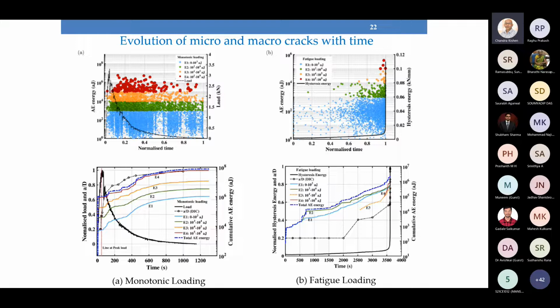But then with increasing crack mouth opening displacement, we see a gradual increase in the low energy and the higher energy events, and later on it becomes more or less constant. Whereas we see an opposite trend during fatigue loading. In fatigue loading, the energy levels E3 and E4 occur only after 70 or 80% of the fatigue life. We don't see them occurring in the beginning. Whereas energy levels E1 and E2 we see occurring at the beginning, and also the crack growth.